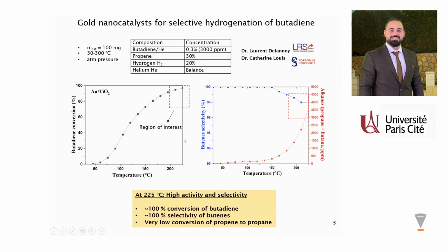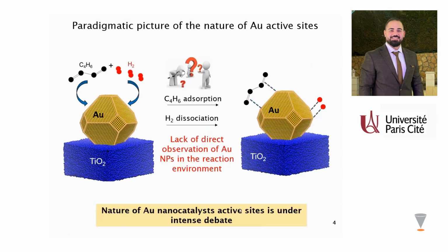So what about the reactivity of gold nanocatalysts during this reaction? We studied, in collaboration with Dr. Laurent Delannoy and Dr. Catherine Louis at Sorbonne University, the catalytic performances of TiO₂-supported gold nanoparticles between 30 and 300 degrees Celsius. The results show high catalytic performances of gold nanocatalysts, showing full activity of gold nanoparticles between 200 and 250 degrees Celsius with full selectivity to butenes. The question is, how will these gold nanocatalysts work in real conditions?